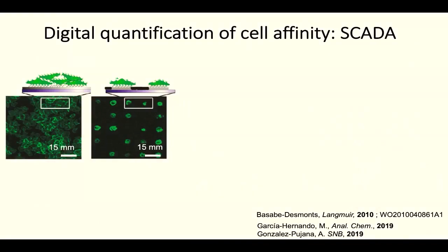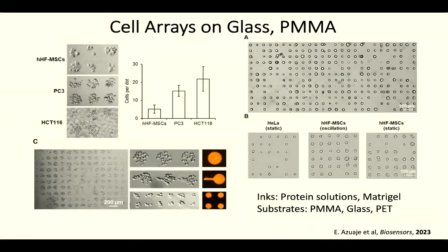But actually, I wanted to put attention to this picture. What you see in there is an array of single cells. By controlling the size of the pattern, I can control the number of cells in each area. So we decided to do arrays of single cells. What we found is that by doing these arrays of single cells, we got a very easy way to quantify the number of cells that are adhering to a substrate, or that are captured in a substrate.